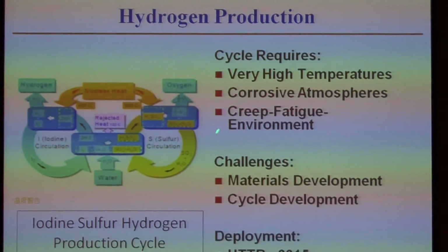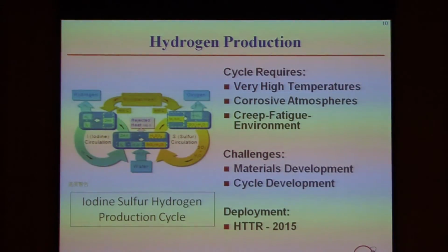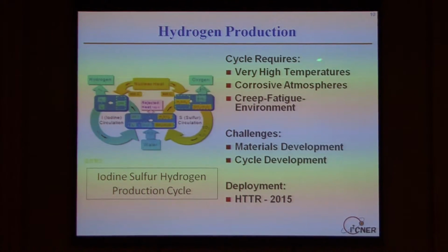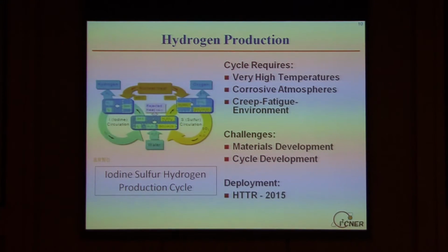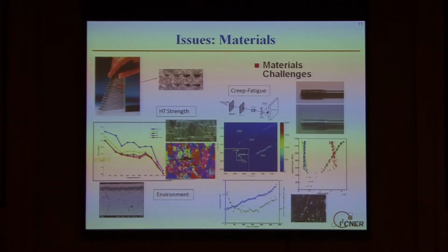The problem with this system, of course, is that the cycle requires very high temperatures. I'll say a couple words about materials in a minute. Corrosive atmospheres and all kinds of other things that are very difficult for materials to withstand. Not so different, but in a different temperature range and a different atmosphere than some of the lower temperature issues with hydrogen and materials. And so materials development is a big issue, and also this particular cycle on a large scale hasn't been proven yet. And so this has to be done. But as I said, this is under development now and will be deployed by 2015 at HTTR here in Japan.